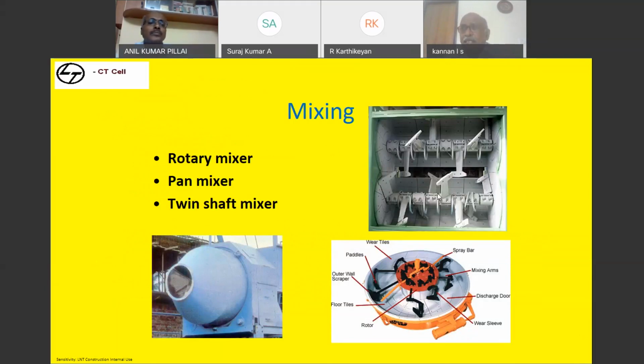Normally the twin shaft mixer is used for producing concrete with either a lower slump or a higher slump. Generally, it is used for making PQC, so that pavement quality concrete with 30 to 40 mm slump can be produced very effectively with twin shaft mixers. When you go with pan mixers, which are the most commonly used batching plants across the industry, plants are available with capacity between 30 cubic meter to 120 cubic meter per hour.